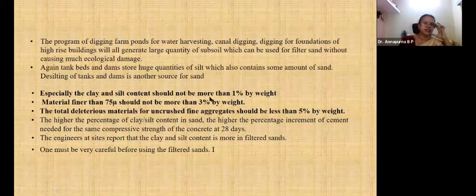Especially, the clay and silt content should not be more than 1% by weight. Material finer than 75 micron should not be more than 3% by weight. So the total deleterious material for uncrushed fine aggregates should be less than 5%. The higher the percentage of clay and silt content in sand, the higher the requirement of cement will be, with the increased presence of clay and silt in the sand.